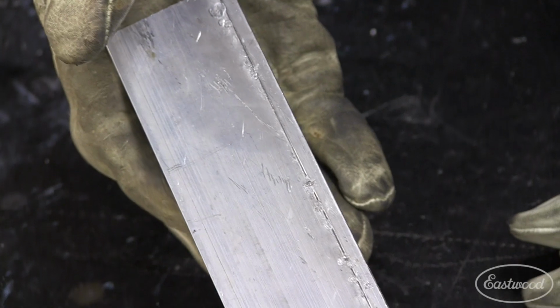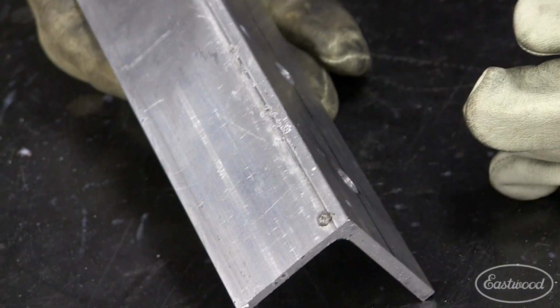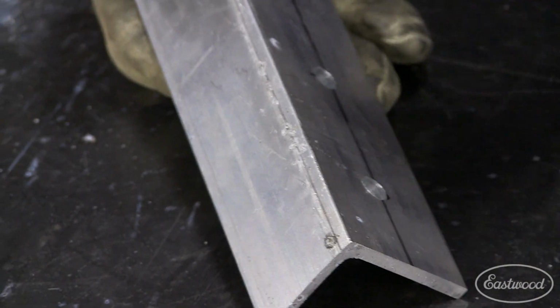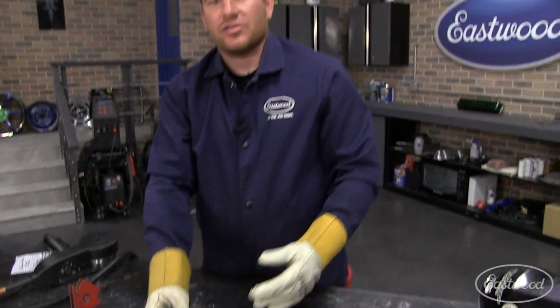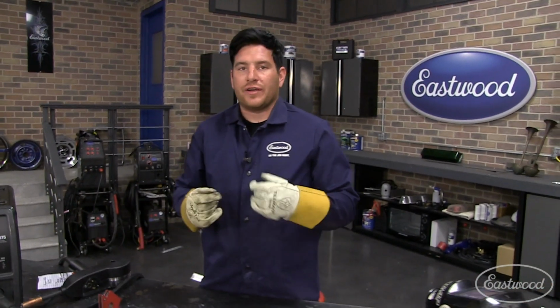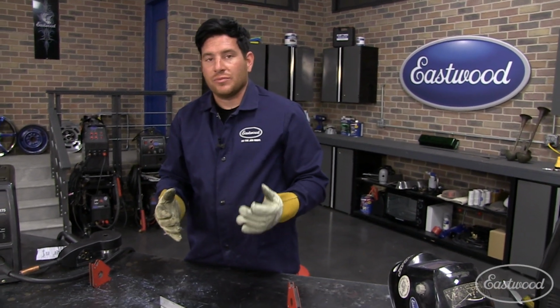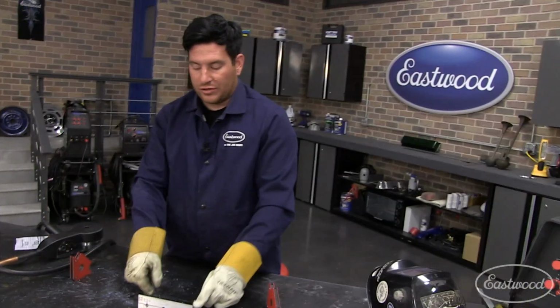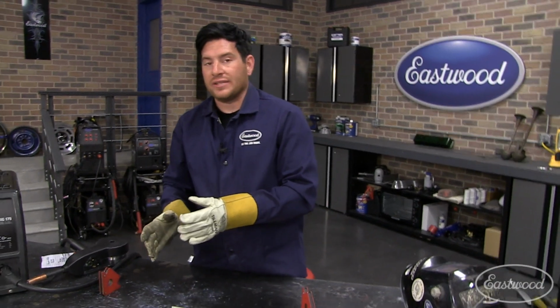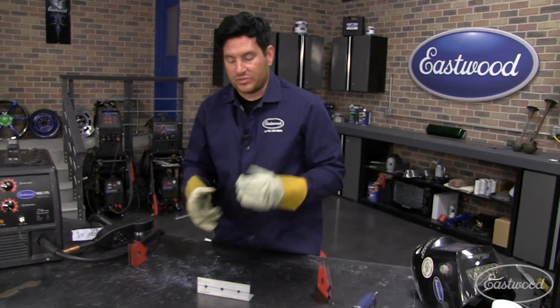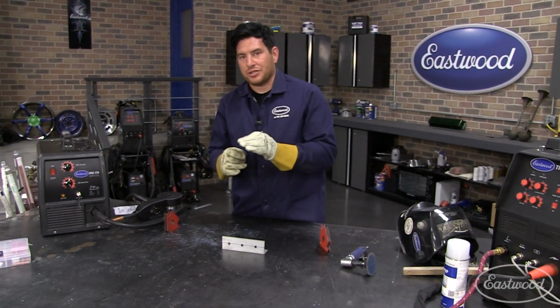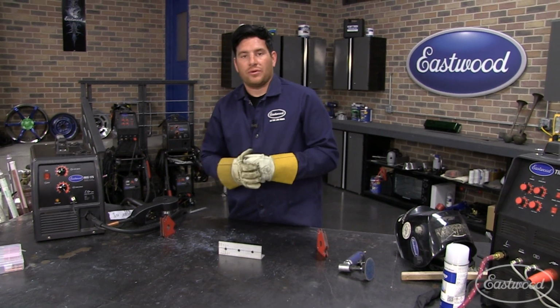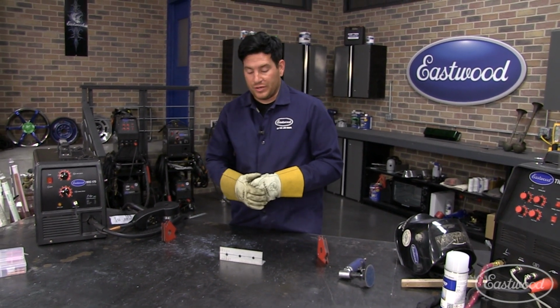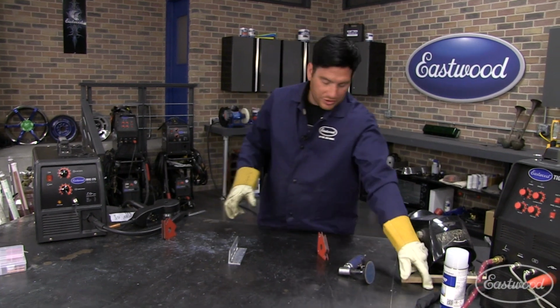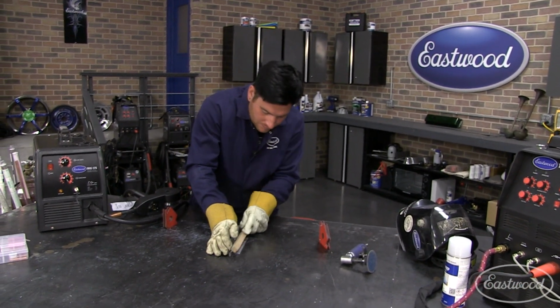The other big problem is aluminum is a heat sink. So as you're welding, about halfway through, the piece is going to start heating up. And with a MIG welder, there's no way to vary the heat, so you need to move faster. As you get more to the end, you actually need to move quicker, because the piece is heating up and you're at a greater risk of burning through. So you really gotta keep an eye on the penetration that's happening with your weld so that you don't burn through. It's really important on MIG welding. So I'll hit this with the wire brush here. I'll show you what it looks like after you're done.